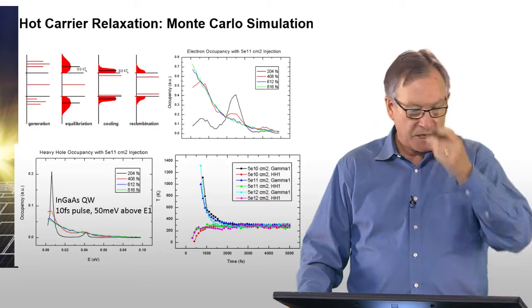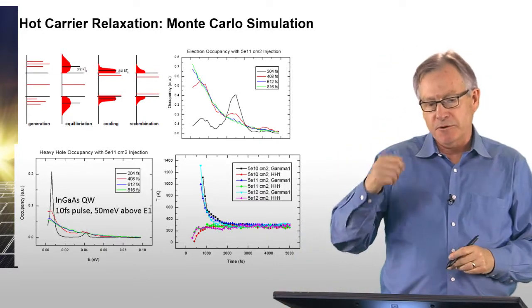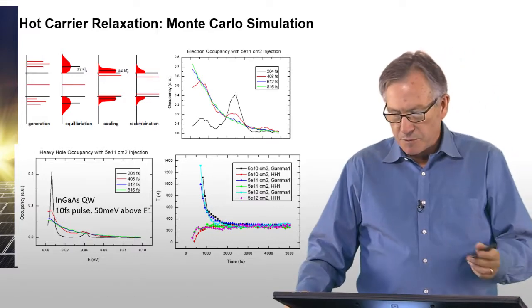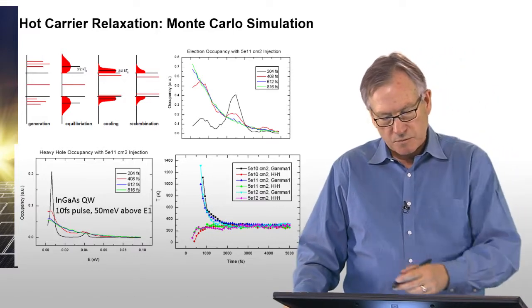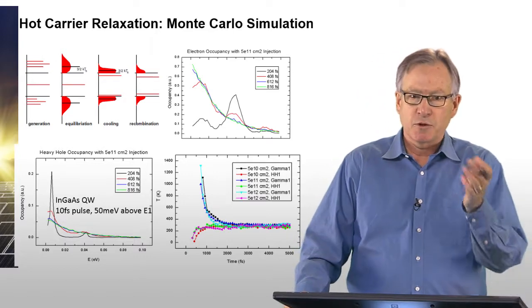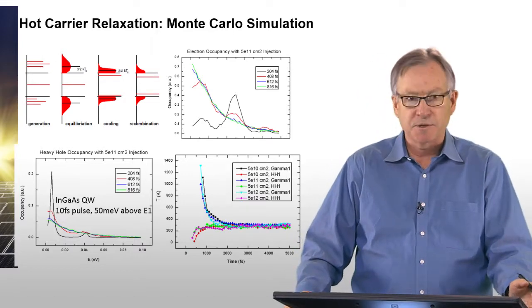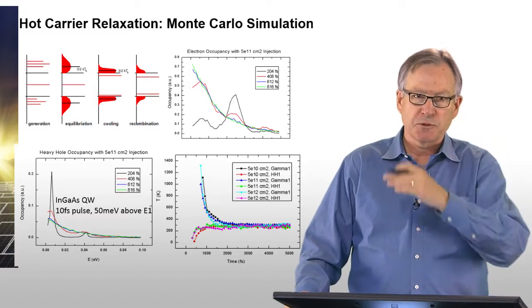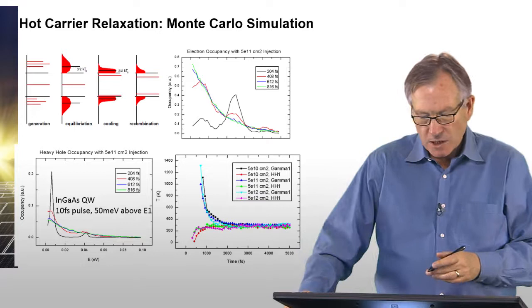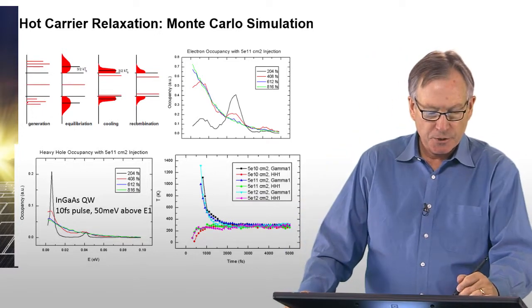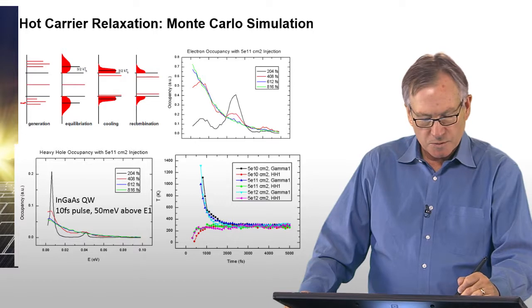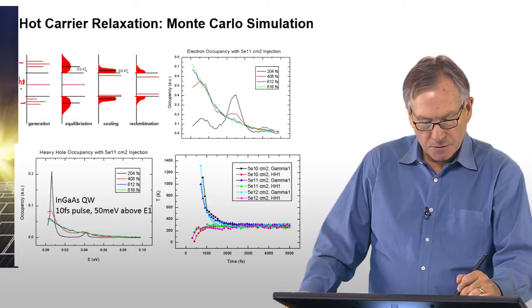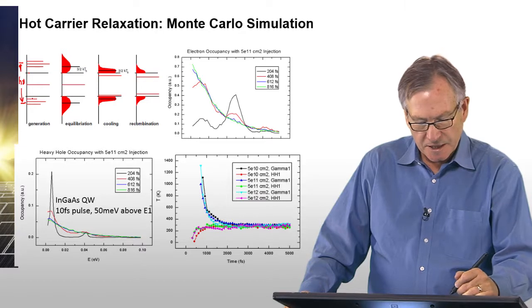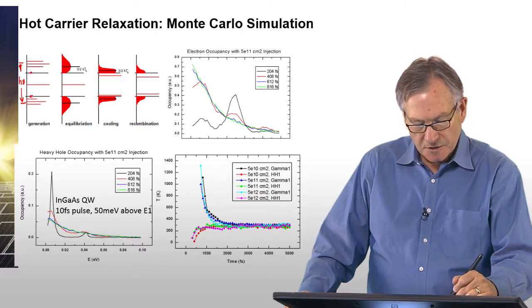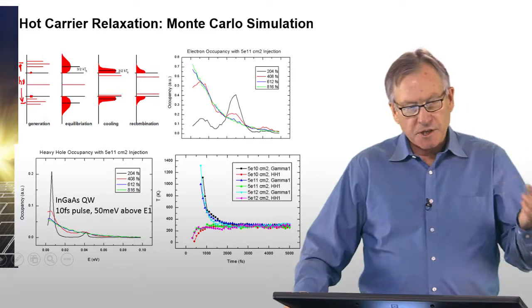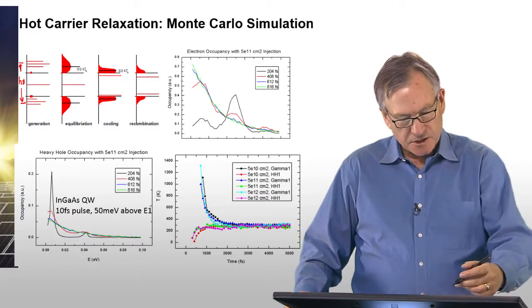This is a schematic of what happens at short time scales in terms of carrier dynamics. This is partly Monte Carlo simulation, but this is also observed in ultra-fast or femtosecond optical spectroscopy, where one can actually study the evolution of the distribution function of the carriers with time. So if you pump a semiconductor material with a laser with a certain energy that corresponds to h nu equal to this separation, this is the conduction band, and this is the valence band. Initially, you create a population of carriers that's completely out of equilibrium.